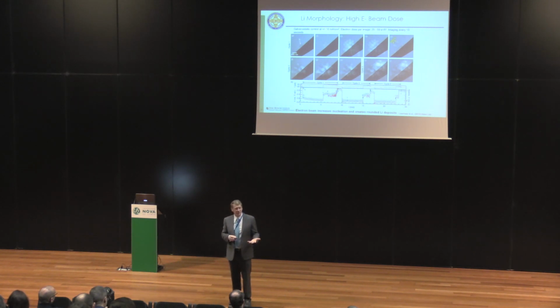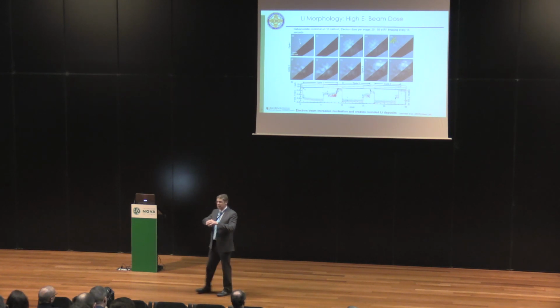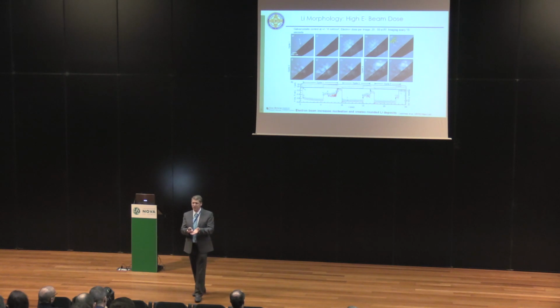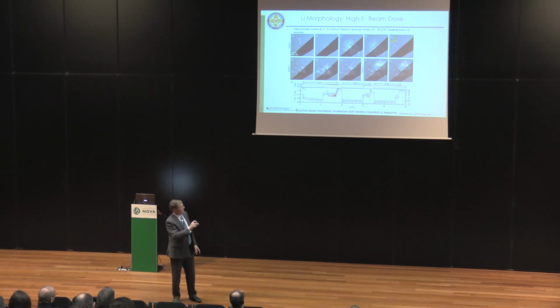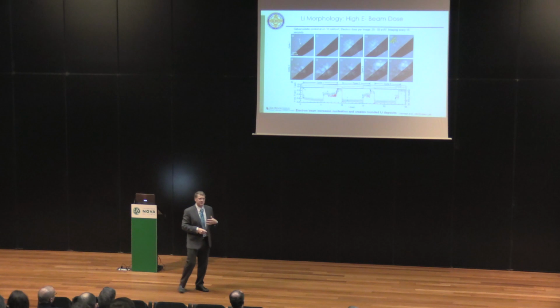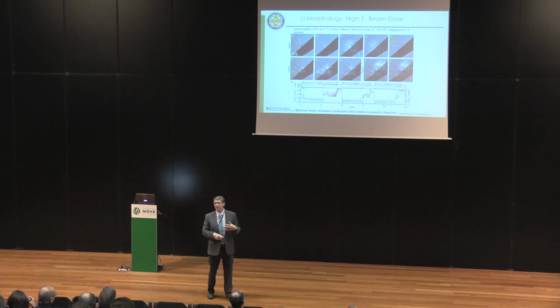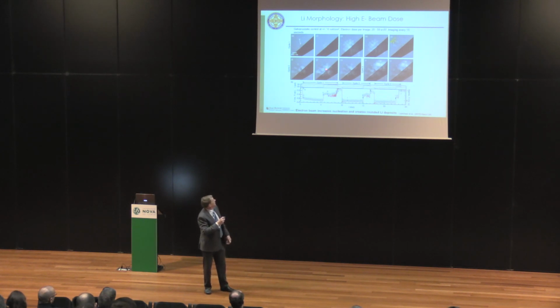So when you deposit from ethylene carbonate, the electrolyte breaks down and forms a shell over the surface. That's the residual shell that you're seeing. Actually, the energy storage community has gotten very good at tailoring this SEI layer and the chemistry of this SEI layer. So what used to be a problem they've changed into a feature. When you start the second layer of plating now, you can see new globes forming,